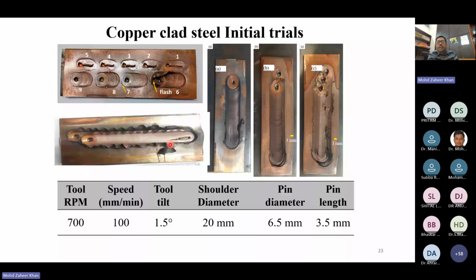So this was having fine grains of approximately 8 to 10 micrometer grain size of tungsten carbide, and this was firmly bonded with some binder. The binder that was used in our tool was cobalt, and the percentage of cobalt was approximately 7 to 10%. With different materials, with different vendors, we obtained different results, but 7 to 10% was working fine. The material of the binder was cobalt, and the tool was mostly tungsten carbide.